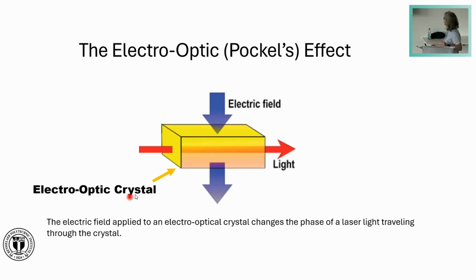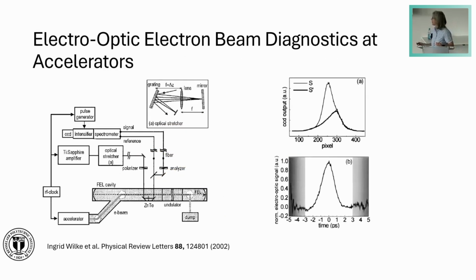So if I have an electro-optical crystal and I apply an electric field to the crystal, and then I pass linearly polarized light, which is generally laser light, through the crystal, then the polarization of the laser light is modified, and the change in polarization is proportional to the strength and the direction of the electric field. So if we bring such a crystal in the vicinity of an electron, the electric field of the electron will modify the properties of the material, and we probe this change with the laser. Okay, this is an early example of electro-optic beam diagnostics at accelerators.